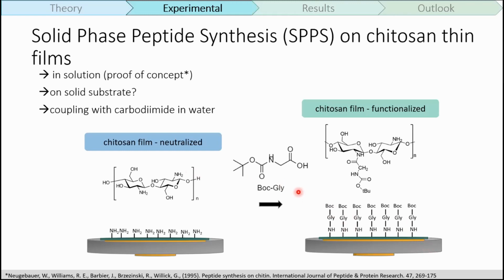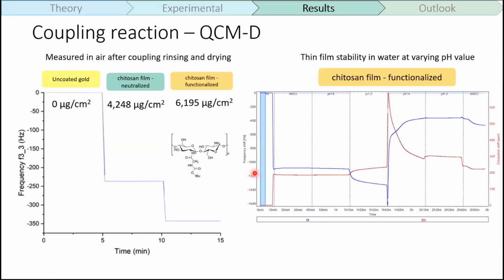We coupled the protected amino acid Boc-glycine with the coupling reagent carbodiimide and measured the change in mass after the coupling reaction inside the QCM. The mass from our film to the functionalized film rose by about 2,000 micrograms per square centimeter. So it's a step in the right direction, showing that something is actually happening on the surface and something is being bound to it.